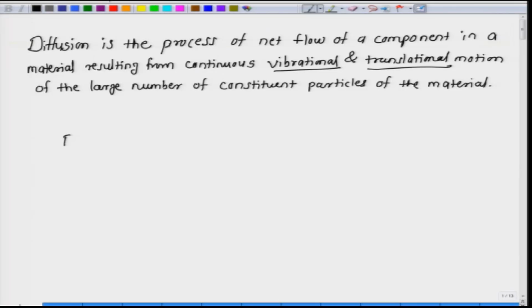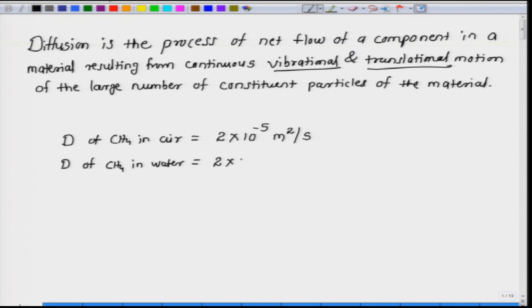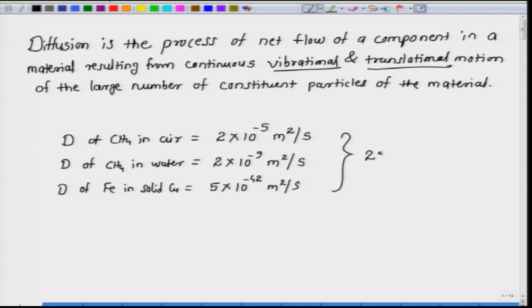As an example, if we want to compare the various diffusivities in different materials, different media. So, for example, if we write the diffusivity of methane in air, that is around 2 times 10 to the power minus 5 meter square per second. The diffusivity of methane in water is around 10 to the power minus 9 meter square per second. And if you look at the diffusivity, let us say, of iron in solid copper, you will find it is around 10 to the power minus 42 meter square per second, right. All these values are at 298 Kelvin.